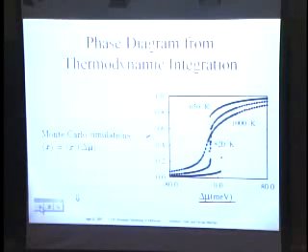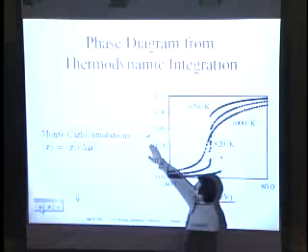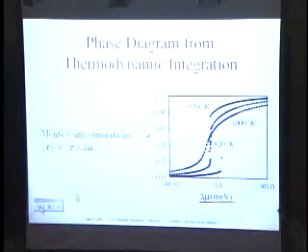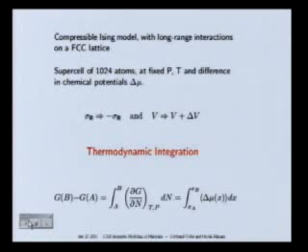That is, you sweep all your possible chemical potentials, and for each choice of chemical potential, you get a certain average concentration. And so you do this over and over again, and what you get is a curve that tells you the concentration as a function of the chemical potential. And you get one of these curves for each temperature at which you do the simulation. So you get concentration as a function of chemical potential, and if we go back for a moment to the previous slide, this is really the inverse of what you need.